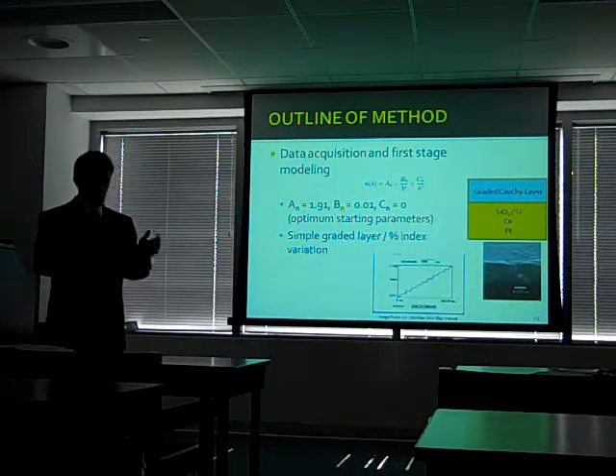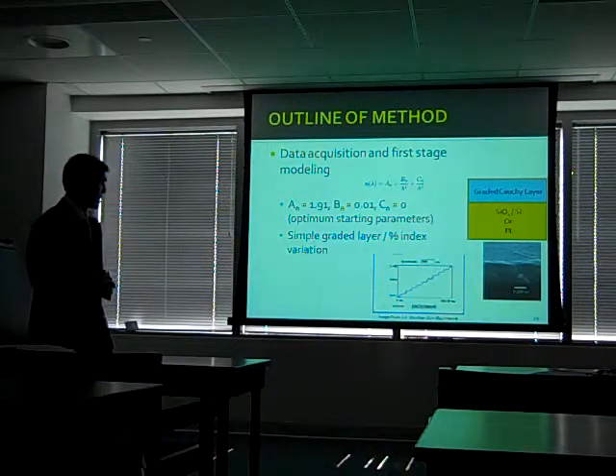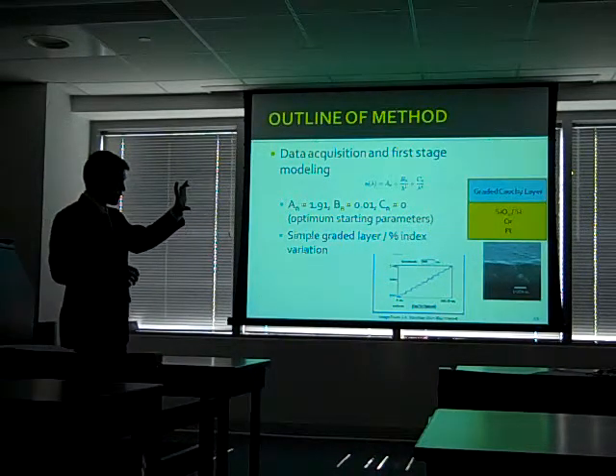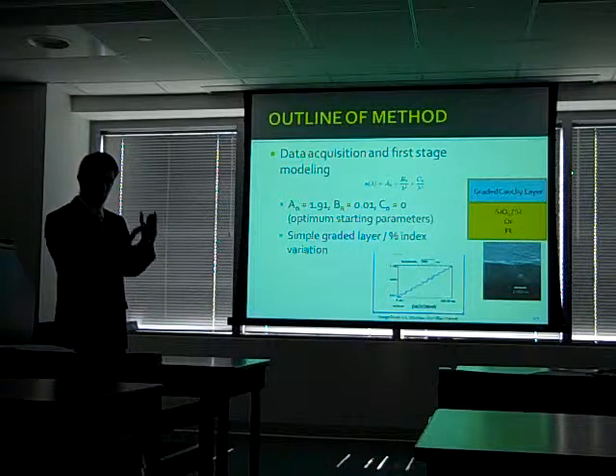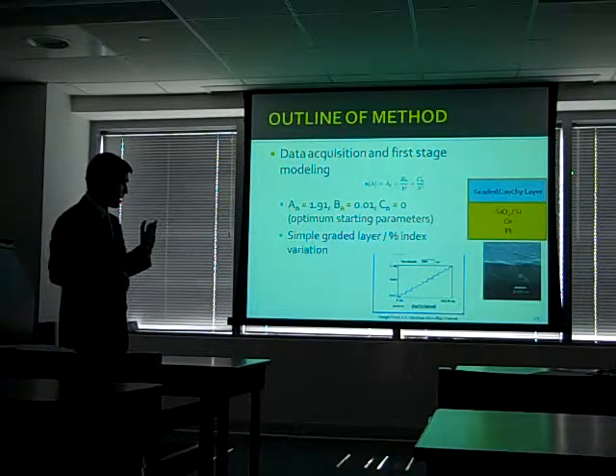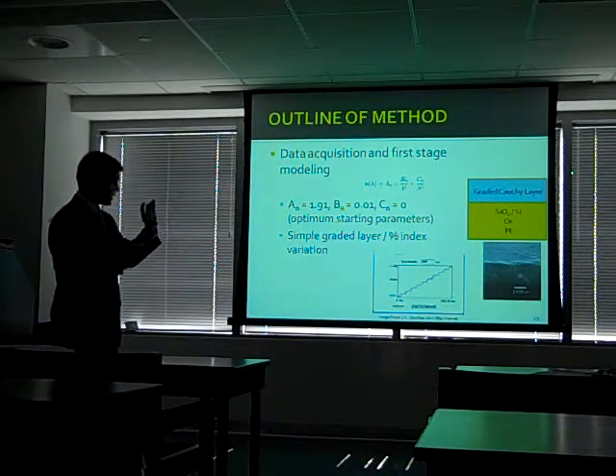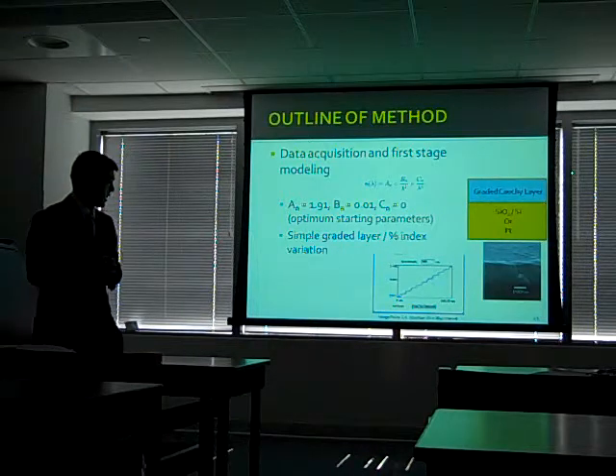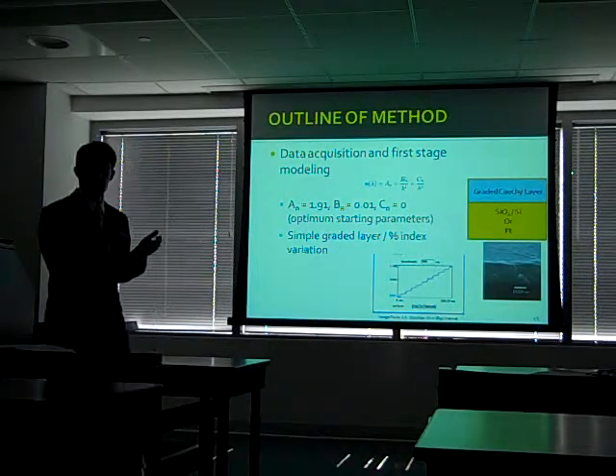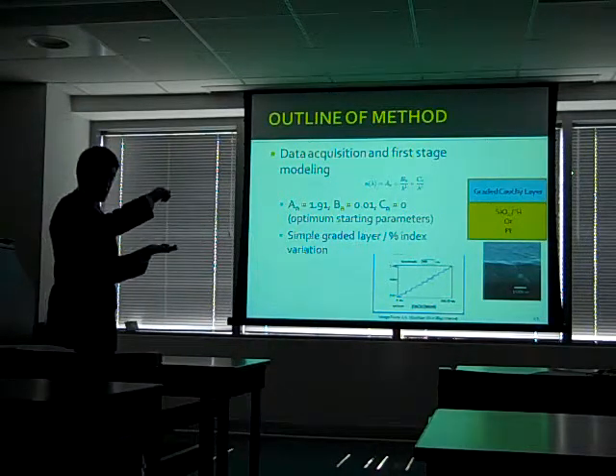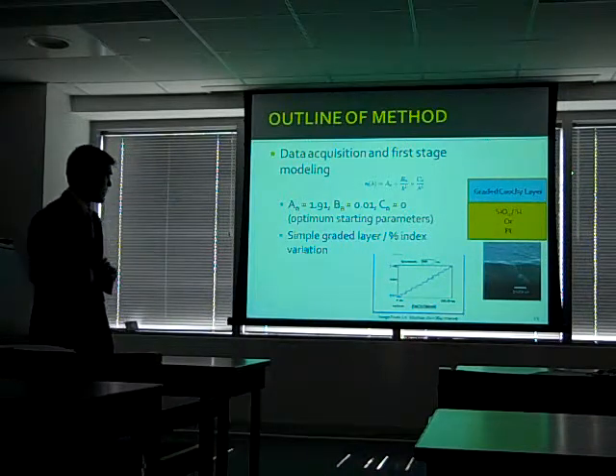Then I found a way to further improve the fit is to convert the Cauchy layer, which is again a parametrization of the optical functions, to a simple graded layer. And what that simply means is that the index of refraction is going to vary as a stepwise function across the thickness of the film.